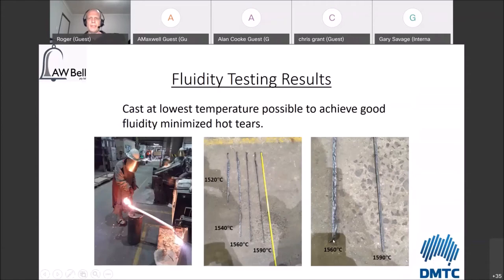But when you look at the characteristics of the material, you can see that the one at 1560 is pretty chunky. The one at 1590 was almost like foil. It just ran incredibly quickly, and this is the one that was shown in the video that was running so fast. So whereas our initial estimate for starting our testing was 1660 degrees Celsius, we found that by doing this, we could drop down to 1590 and still get extremely high fluidity in the material.